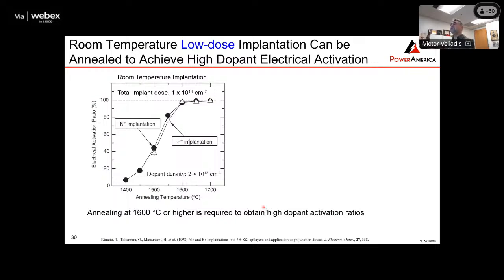And just to give you an idea about the room temperature implantation. If you do the implantation without heating the wafer, you can see that when you anneal the wafer, you get almost 100% activation as long as your dose is low. So these results here are for low dose. If your dose is low, below 10 to the 15th, then if you do an implantation at room temperature, you don't use heat, then you can get very good activation of the dopants.